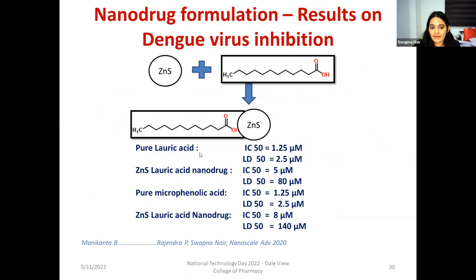You can see the lauric acid, which is a drug used as an antiviral agent. So its therapeutic index is very poor. Therapeutic index means its inhibiting concentration is 1.25 micromolar, while the lethal dose for killing 50%, which shows the toxicity limit, is only 2.5. So that means if I take paracetamol 500, I will get my pain relieved, and if I take paracetamol 1000, I will die. So that doesn't make any sense, because the therapeutic index is too narrow. We will not be able to use that drug for any practical application.